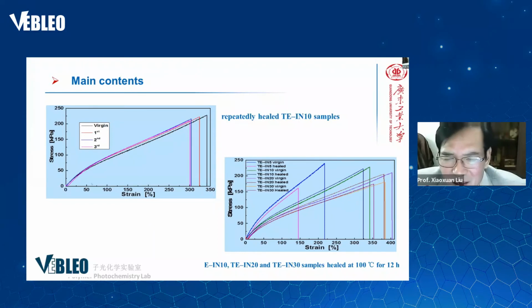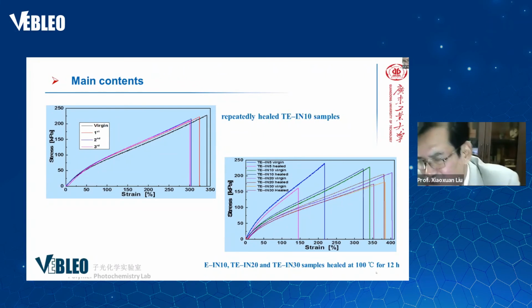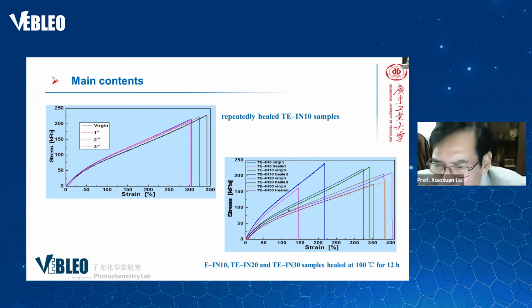So it is the mechanical properties. It is persistent after repeatedly healing the TE-IN10 samples. It is persistent at the highest stress. When it is the strength, there are no changes. So the virgin is black, and one time, two times, and three times. So this is the difference of the sample healing at 100 degrees for 12 hours. So it is like this.